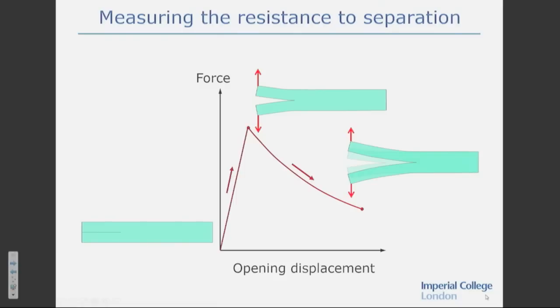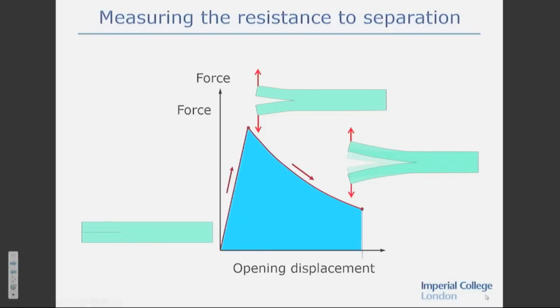Now, of course, the work done by a constant force is just force times distance moved in the direction of the force. If the force is varying like that, well, it's just the area under the force displacement curve. So this represents the work done, or the energy that's being put into the system to change the specimen from this to this, which contains a longer crack. Now, of course, in this state, it still contains energy because these arms are still bent. If we unload it, though, we'll get this much energy back out, and the specimen will be in this configuration. So the energy absorbed in growing the crack from this position to this one is just the area of the blue zone here, and I've called it U. Okay. So the crack's grown, of course, and the area that the separation front has swept through, I'm going to label it A, and then I'm going to tell you that this separation toughness, often represented by G1C here, is just the energy divided by that area. Okay.